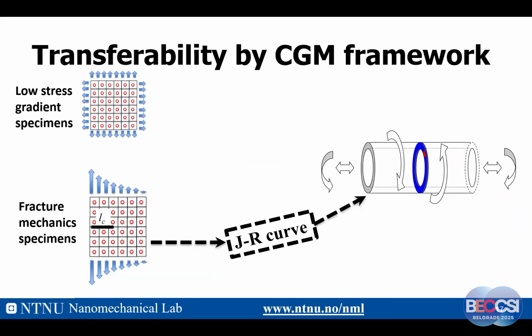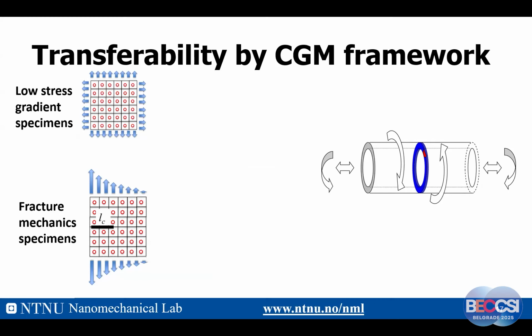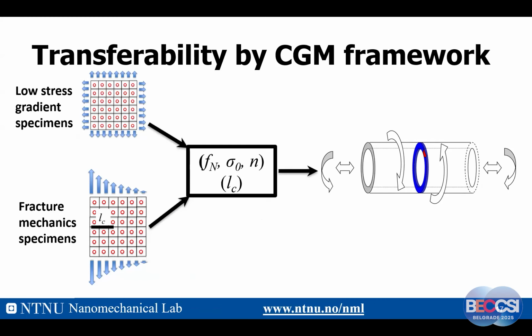And this is one of my last slides. Transferability: we should have a resistance curve. We could have J-R from a fracture mechanics specimen and apply it to the component. But in fact, due to the constraint, this is not working. Then we can have transferability by the void nucleation parameter plus a characteristic length parameter, LC.